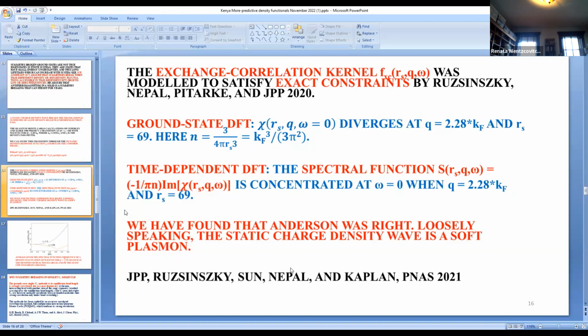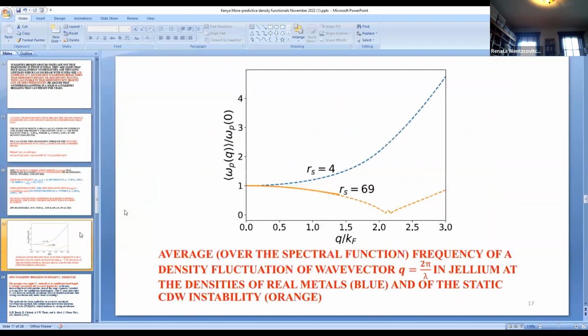What we found is that Anderson was right, and loosely speaking, the static charge density wave is a soft plasmon—a plasmon that drops to zero frequency. I'll show you a figure that illustrates that. It's this figure.